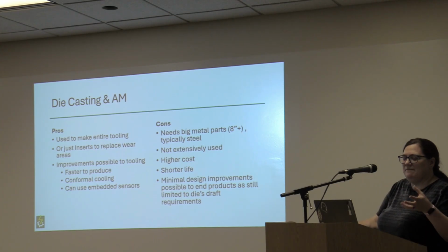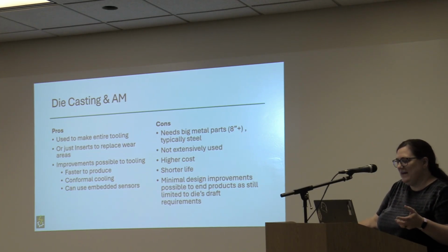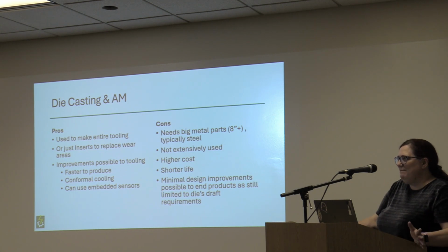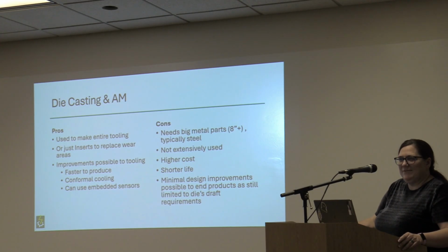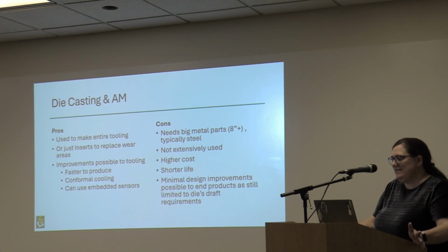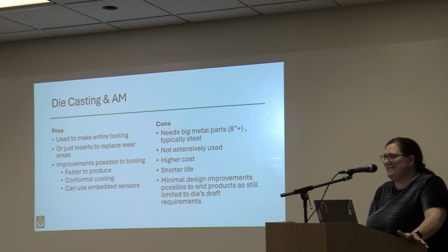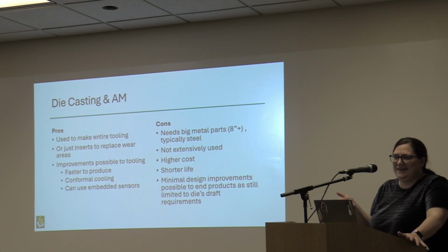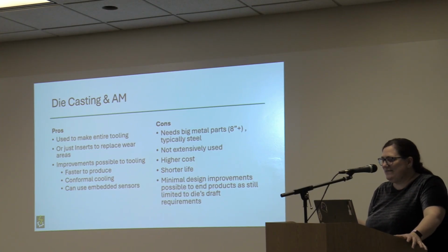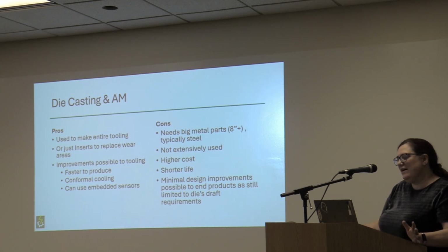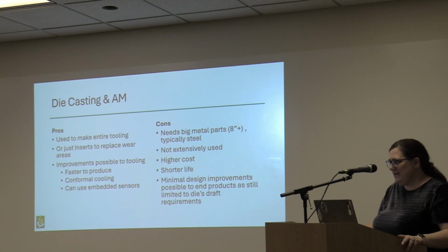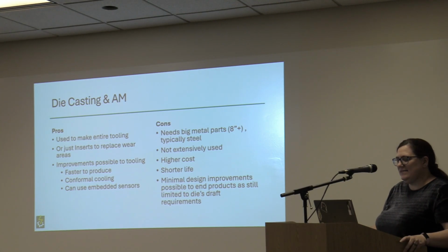It's also sometimes possible to iterate faster if you're using the added versions. But big cons in that typically die casting is still going to require a metal tool, possibly for permanent mold you might be able to have aluminum or copper depending on what you're trying to cast. But typically these are steel and they're relatively big, so now you're going back to this original problem that these printed metal parts are very expensive. So people are not typically printing the whole tool, although sometimes they are doing this for conformal cooling benefits, just because of the cost.